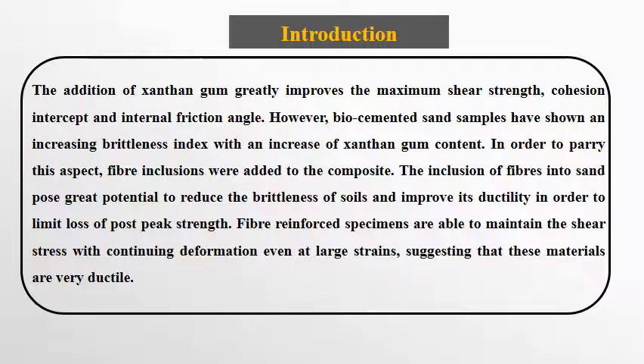The addition of xanthan gum greatly improves the maximum shear strength, cohesion intercept, and internal friction angle. However, biocemented sand samples have shown an increasing brittleness index with an increase of xanthan gum content. In order to parry this aspect, fiber inclusions were added to the composite.